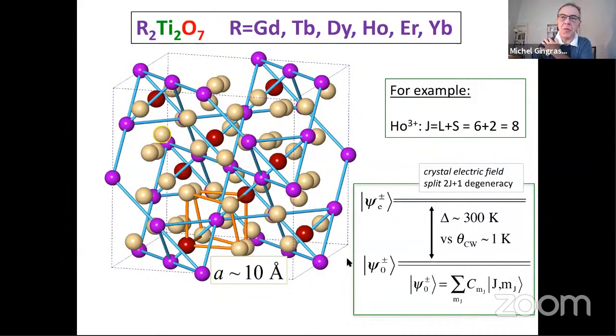And so what one finds is that for holmium, the ground state is a doublet, and the next excited state is also a doublet, and the energy gap between these two doublets, in temperature units, is about 300 Kelvin. So there's a huge separation of energy scales between the crystal field levels of holmium and dysprosium, which is much, much larger than the typical energy scale defining the interactions between the rare earths, which is of the order of 1 Kelvin. So for all practical purposes, at low temperature, where the system starts to develop magnetic correlations, one can neglect the thermal population of all crystal field energy levels of these systems, except the ground crystal field doublet.